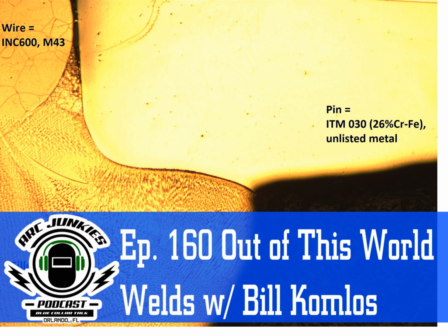Right. You get cold laps and you're still not punching in, because with spray, you're going to punch in a lot harder than you are with short circuit. You're putting a smooth bead on top of that plate, but you're not punching into the throat. No. And it's not supposed to. That 3/16 limit that AWS likes you to have is there for a reason. Yeah, it's great for sheet metal.